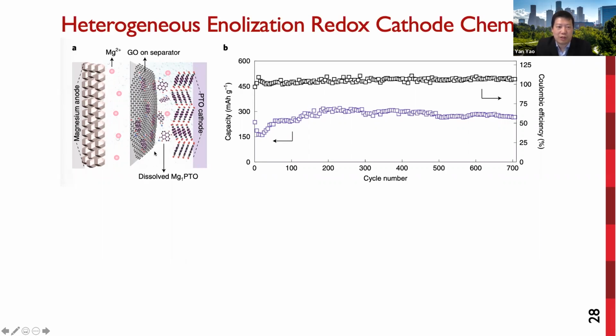Dissolution of PTO is suppressed by inserting a 2 micrometer thin, lightweight graphene oxide membrane between the cathode and the separator to trap the Mg1 PTO intermediate, but still maintain electric contact because this graphene oxide membrane is electronically conductive. So all the capacity trapped by the Mg1 PTO can still contribute to the capacity of the cathode. This concept is borrowed from lithium-sulfur batteries and has proved very effective. The battery has an initial activation step due to the high viscosity of the G4 electrolyte. Then it becomes stable for 500 cycles with a capacity retention over 84%.